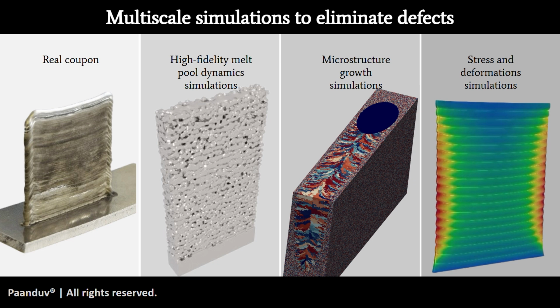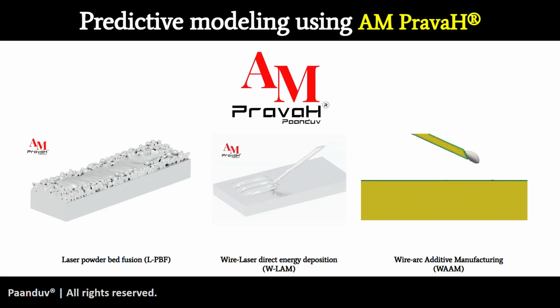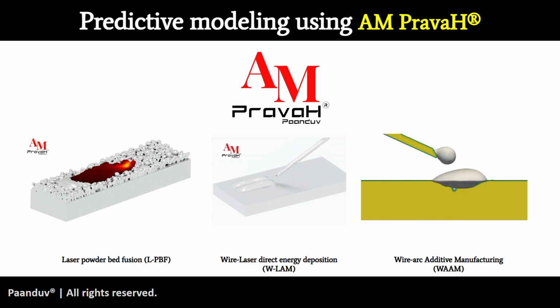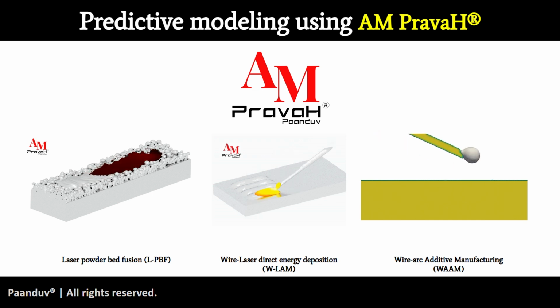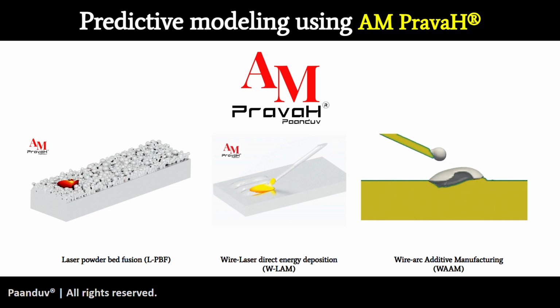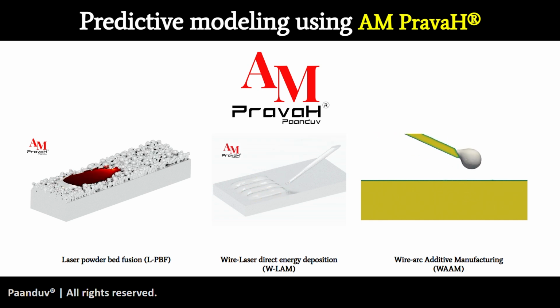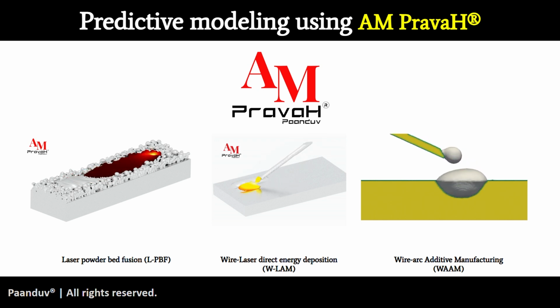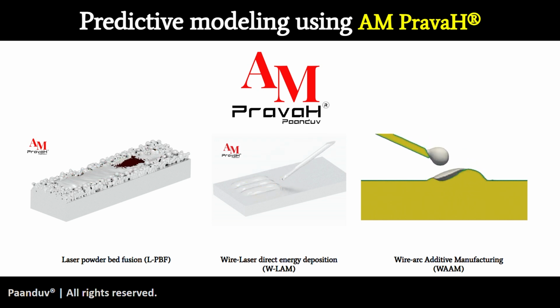The third one is a microstructure growth simulation, the grain evolution of a thin plate. And the fourth one is the stress and deformations simulations, the data associated with the thermomechanical stress analysis using AM PravaH again. So in short, what I want to highlight is that predictive modeling is quite capable of capturing some of the very hidden details about the defects that can happen in 3D printing processes. It can guide us, point us to the right direction as to what must be changed, what must be optimized in order to produce a very good build, irrespective of the process.